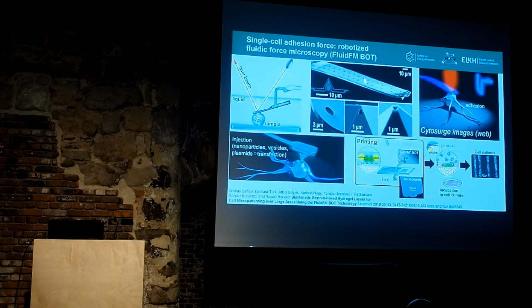And the very first technique we are using is robotized fluidic force microscopy. This is based on a conventional AFM tip, but compared to the conventional AFM cantilever, it has a microfluidic or nanofluidic channel inside, with an opening at the end, and the size of this opening is only a couple of microns. We stick it on the top of the cell, and this pressure control system employs a vacuum, so basically the system sucks in the top of the cell, and one can lift up the cell from the surface. And during this process, the cantilever is bending, and from the bending, one can calculate quite precisely the adhesion force.